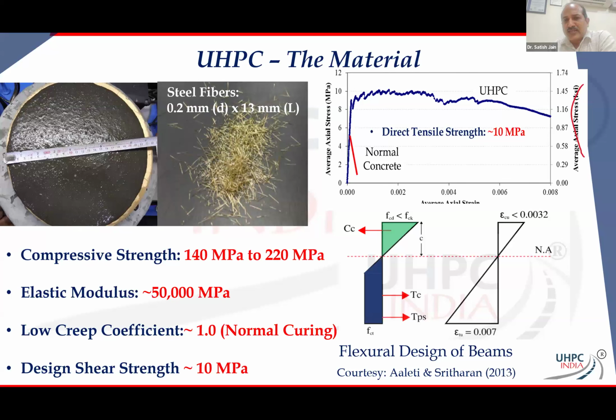And the beauty is that this means that your flexural toughness or the energy dissipation or the energy absorption characteristics are far, far greater than that of concrete. It also means that, for those of us designers over here, you will be able to appreciate that when you take a cross section and you have a neutral axis, typically below the neutral axis, you're not utilizing the tensile properties of concrete. But in UHPC, you just simply take that tensile stress strain curve and you put it below the neutral axis and you're able to get the tensile benefit from the UHPC in design.